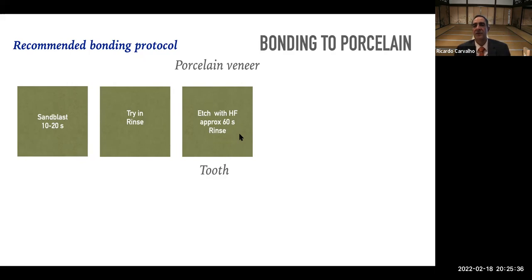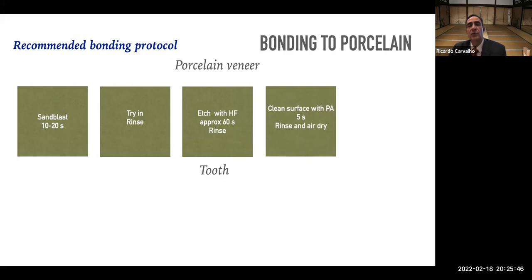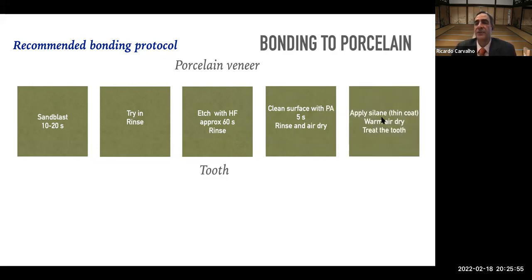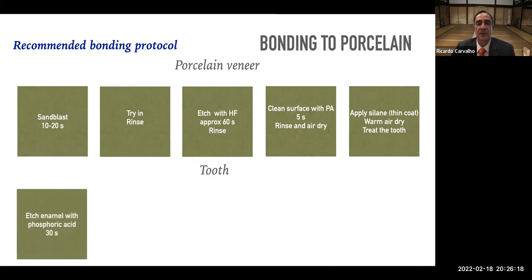If there is any whitish surface, then you either ultrasonicate it for 5 minutes or just apply phosphoric acid for 5 seconds to remove the debris, then you rinse and you dry again, and then you can proceed with your silanization. Remember, always a thin coat, a single coat or double maximum. Warm air if you have it available. In 30 seconds, you are done, or just leave the veneer on the side and go to treat the tooth as a regular procedure for bonding that you will do.